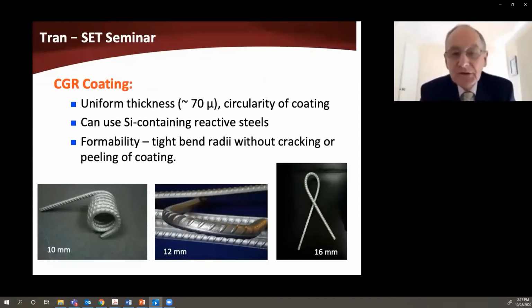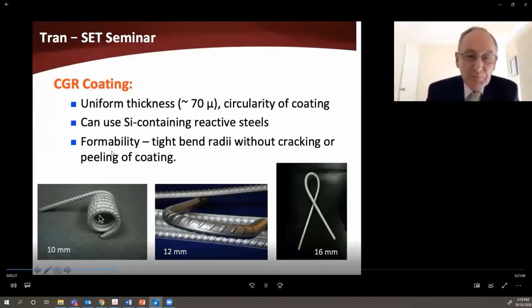But with continuous galvanizing, because the steel is only in the zinc bath for literally a few seconds, and because of additions that are made to the zinc bath, a small amount of aluminium, the nature of the steel does not have any long-term effect on the coating. And of course, it's essentially a pure zinc coating on the surface. And here are just a few pictures, this one here particularly, showing how tightly you can bend this coating without cracking or damage.